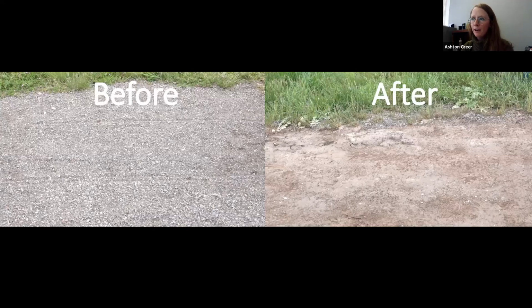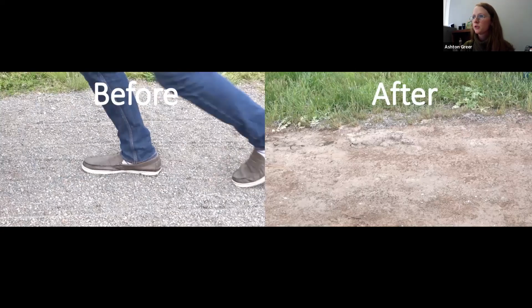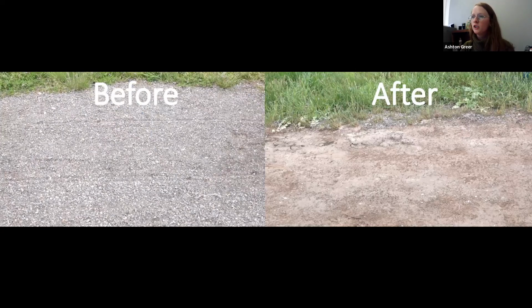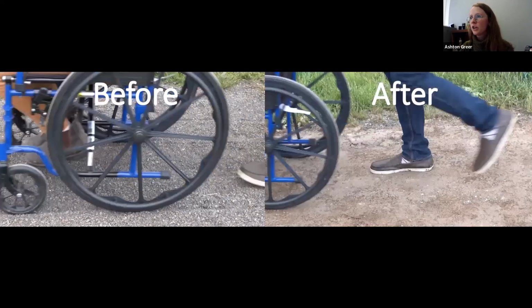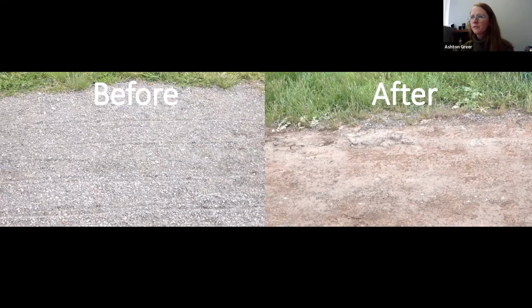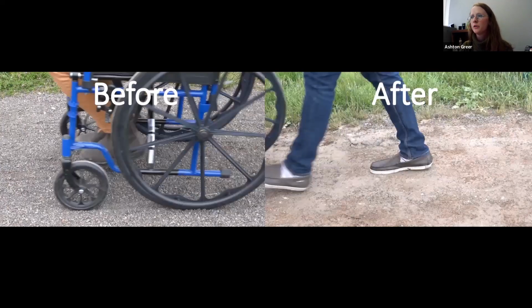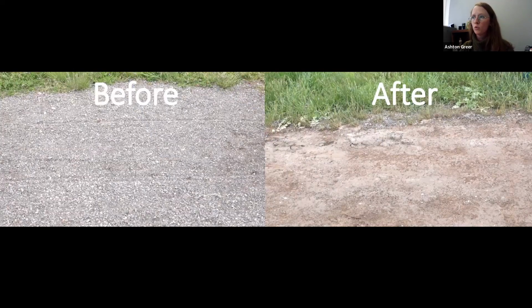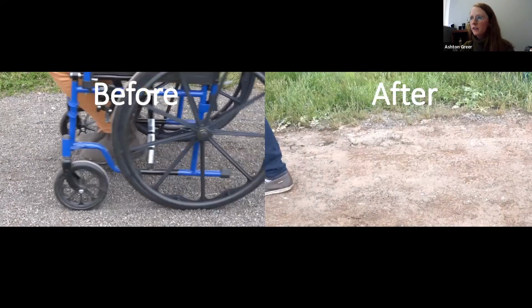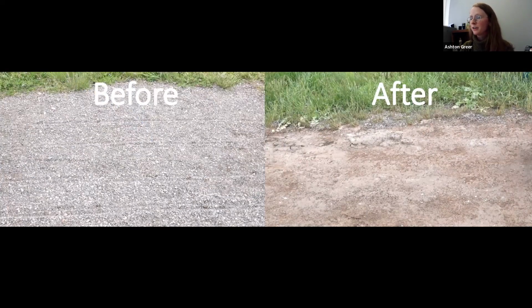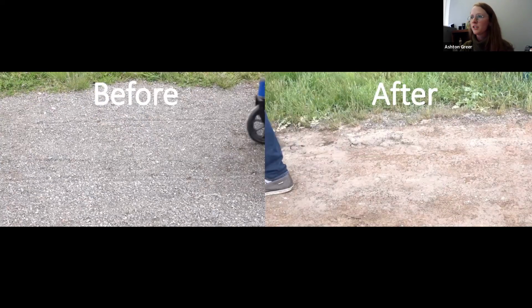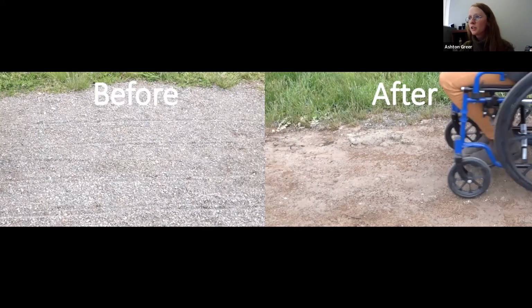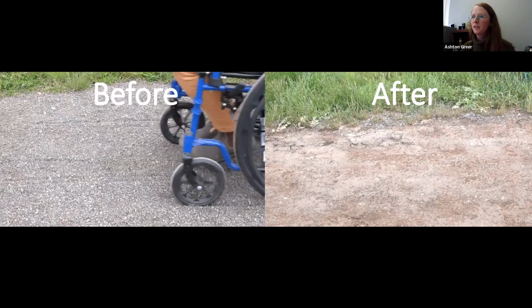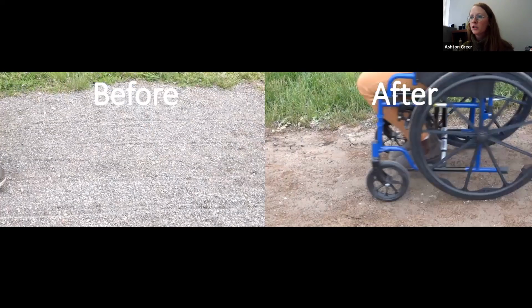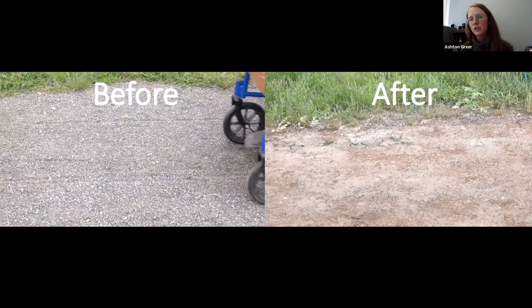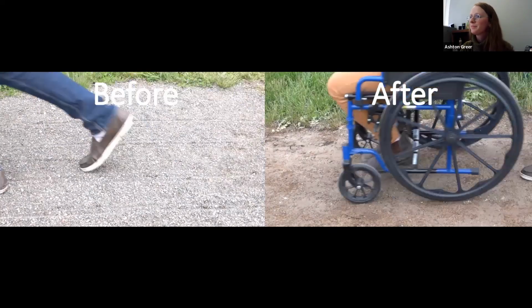So the clip on the left shows the original Geo Trail surface, which is a fairly uniform 3/8-inch aggregate. While it's relatively smooth, you can see the rutting after wheelchair use, and the looser aggregate results in more rolling resistance. So the right-hand clip shows less rutting and kind of associated less rolling resistance from the wheelchair users. So we're going to talk about everything that happened between this before and after video, starting with CJ talking about some of the previous research and motivation behind this project.